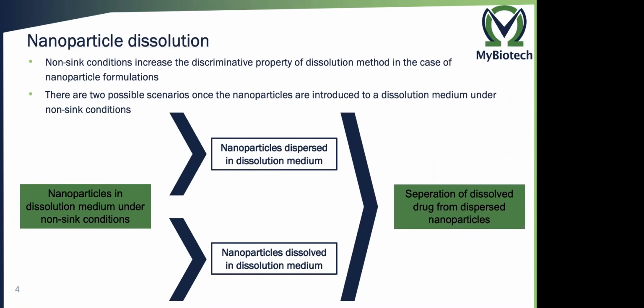First, we need to understand what happens to nanoparticles when I put them under non-sink condition. So I take the nanoparticles, I put them in the dissolution medium under non-sink conditions. Two possible things can happen. Some of the nanoparticles will be dissolved in the dissolution medium, and some of the nanoparticles will only be dispersed in the dissolution medium. And according to the definition of a dissolution study, only the nanoparticles dissolved in the dissolution medium have an effect on bioavailability, which means that I need to separate the nanoparticles dispersed in the dissolution medium from the medium which contains dissolved API.